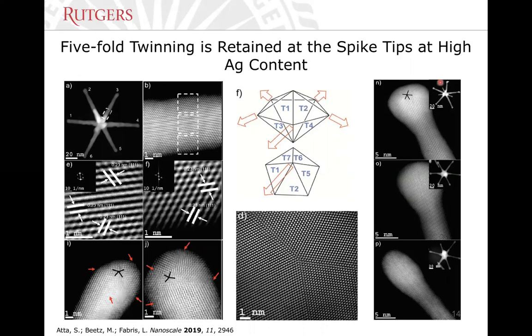Another interesting thing is that if we look at the growth of the spikes, we see that this 5-fold twinning, or the morphology of these particular corners from which the spikes grow, is retained. And as you can see, these are the heads or tips that we've analyzed. And another interesting thing that we have observed, if you look at the right side of the slide, is that if we have a high amount of silver nitrate, and therefore a low amount of metallic silver on the nanoparticle, we start at short times after synthesis with this 5-fold twin. If we don't have enough silver, we have a complete reshaping of the spike, and also the loss of the 5-fold twins. So you can see here this is one spike examined at different times, and there's a complete reshaping and restructuring of the spike.